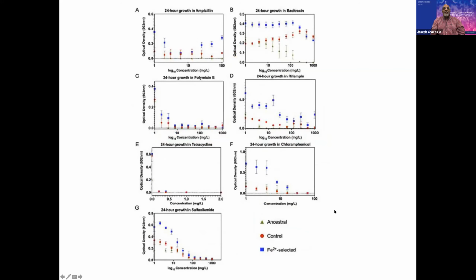Now, another interesting result of these experiments that again could not have been predicted from the initial proposition was that antibiotic resistance was also a correlated trait with iron 2 resistance. So the iron 2 resistant populations became better at growing in ampicillin, better in growing in bacitracin, better at growing in polymyxin, better at growing in rifampicin. There was no difference in tetracycline, strong difference in chloramphenicol, and a strong difference in sulfanilamide.